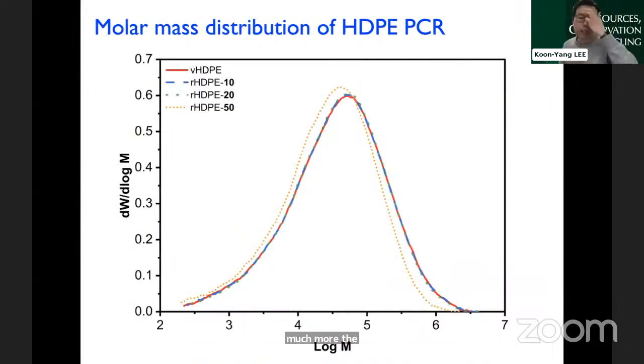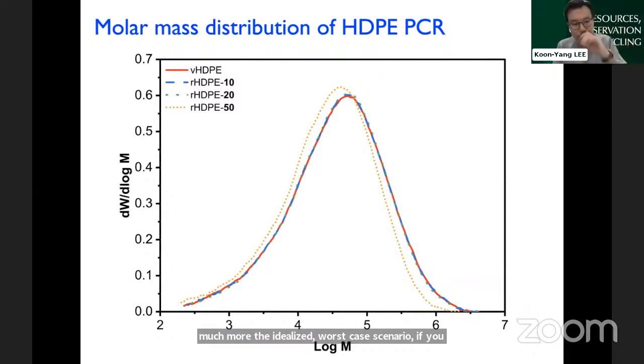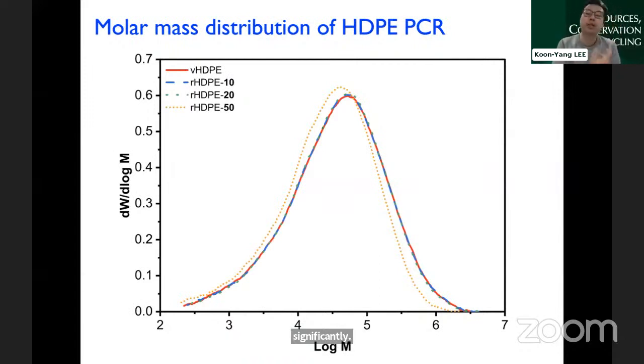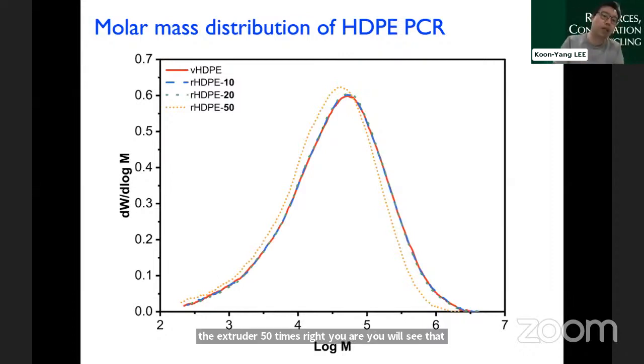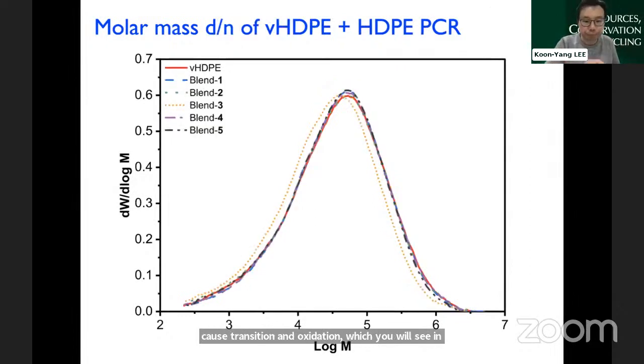All right, so if you first look at the molecular mass distribution, here is just virgin polyethylene comparing with those recycled polyethylene 10 times, 20 times, 50 times, all right? So obviously, polyethylene is a rather sturdy polymer, very stable. So even after 20 times of passing through a rather harsh extruder, if you will, you don't actually reduce the molecular mass significantly. But if you go to the extreme, 50 times passing through the extruder, you will see that your molecular weight shifted a little bit lower just because you now finally cause degradation and oxidation, which you will see in the next couple of slides, right?